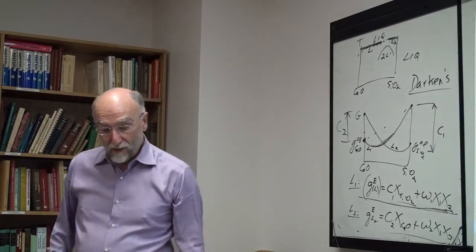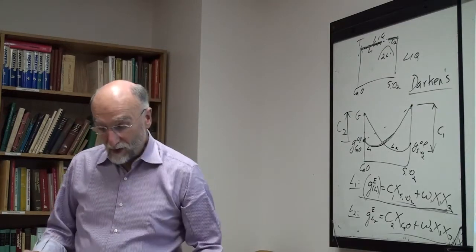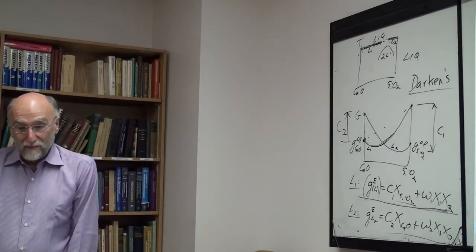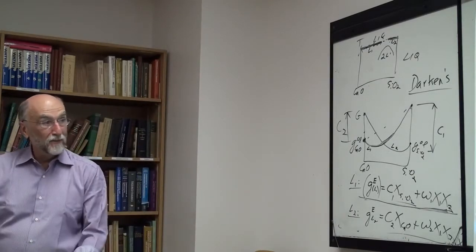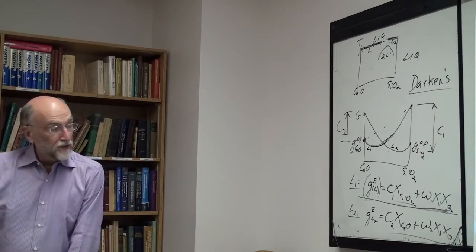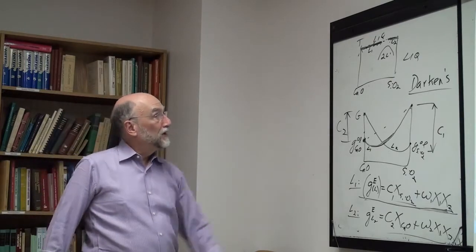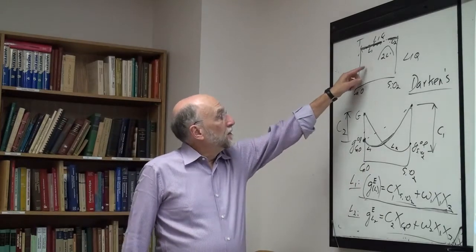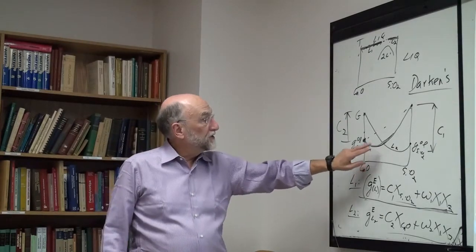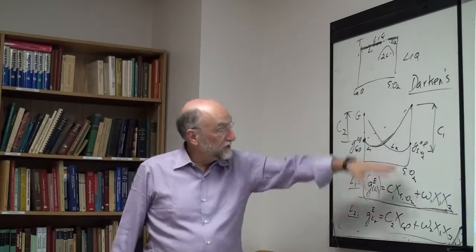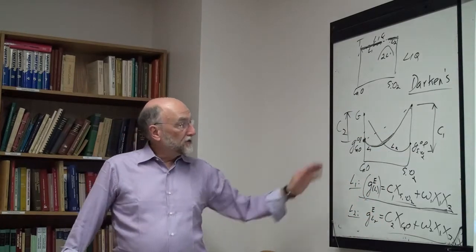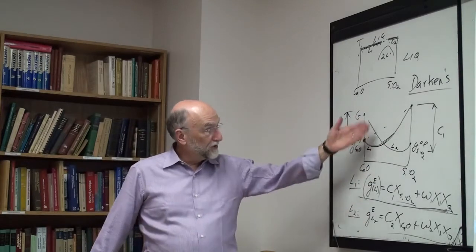Anyway, that's Darken's Formalism, which I'm presenting here to show you a bit more about, not that you'll be using it mathematically, but it shows you something about the structure of materials. Now I had this here for liquid. The same thing would be for a phase, say an FCC phase. If these are two different structures, if this was FCC and this is HCP, then of course you can do it this way because they're not the same phase. They don't have to meet in the middle. But if they're the same phase, FCC, then you really shouldn't do it this way.